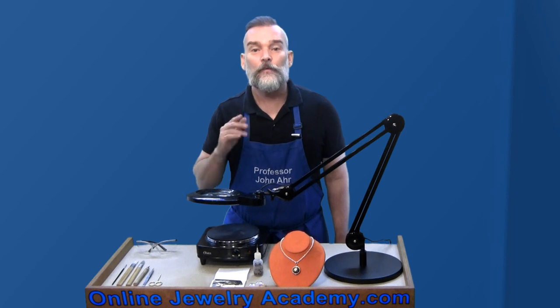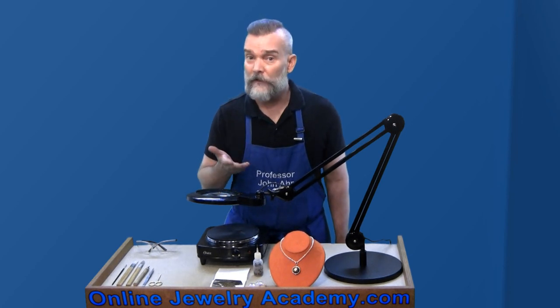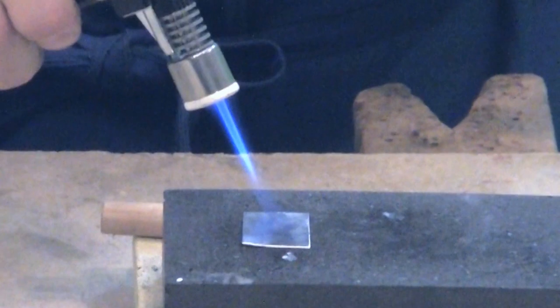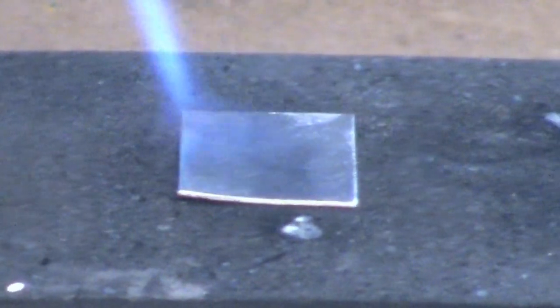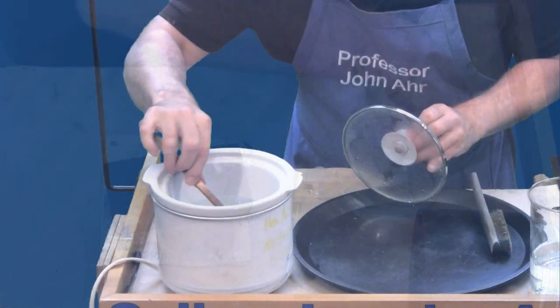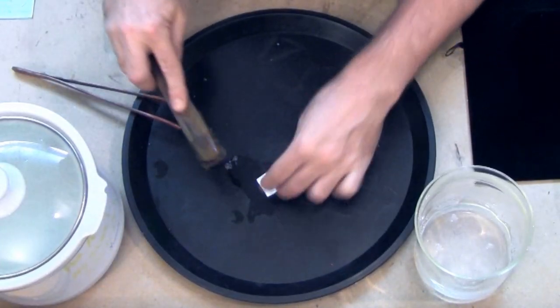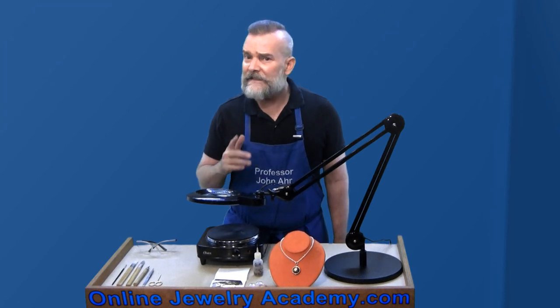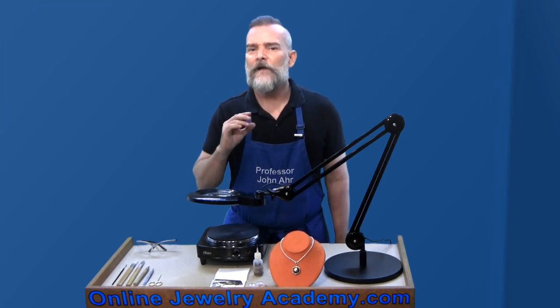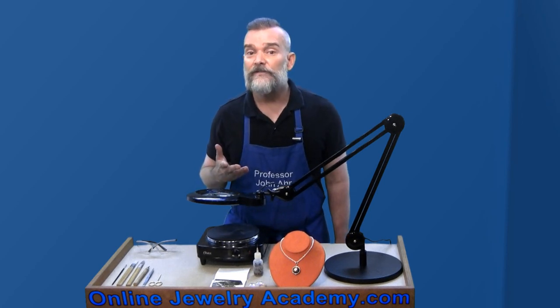Before you begin, you'll need to raise the fine silver on the surface of the piece that you'll be applying the gold to. You do this through depletion gilding. Lightly heat your silver until the shiny surface turns matte, then quench it and put it in the pickle pot. Neutralize the metal, brass brush, rinse and dry. You'll need to repeat these steps at least seven times. You'll know you've accomplished frosting the surface when the application of heat turns the surface a solid matte white.